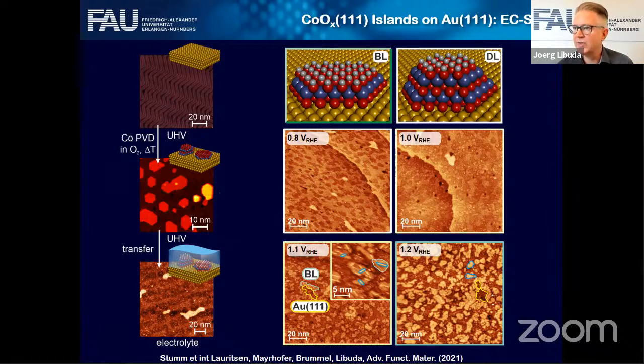But again, you're not free with the choice of the bias. So these are pictures here with different potentials. These are images taken at different potentials. And we have to make sure that the tip is always under a potential where it's stable.